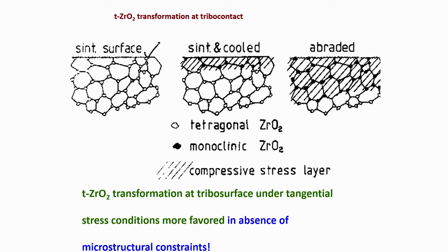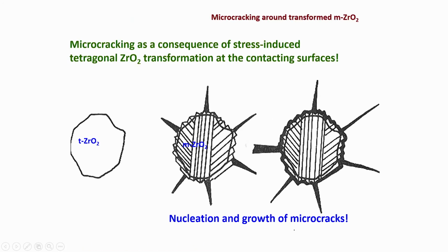So, suppose it is an as-sintered surface, like a hot pressed surface, it is sintered but cooled. That means there may be some phase transformation, and when it is abraded, a compressive stress layer is formed. So, tetragonal zirconia to monoclinic zirconia phase transformation under tangential stress conditions is more favored in the absence of microstructural constraints. And again, microcracking around transformation toughened zirconia: you can see this is the tetragonal zirconia, and then when it transforms to monoclinic zirconia, it causes these microcracks, which can release from the periphery of the transformed phase.